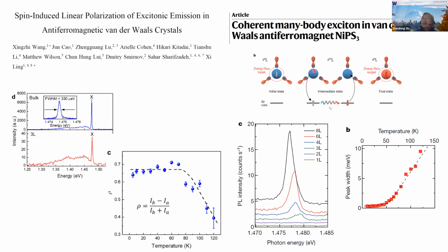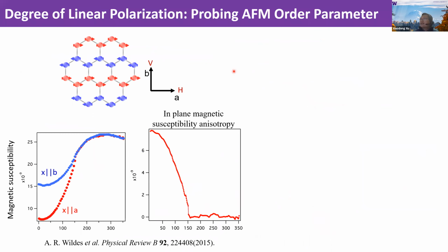But in all this work, we see the exciton has signatures connected to the magnetic order. But where does this optical anisotropy really come from? To address this question, we found this paper, which measures the magnetic susceptibility anisotropies along the a axis and also the b axis.